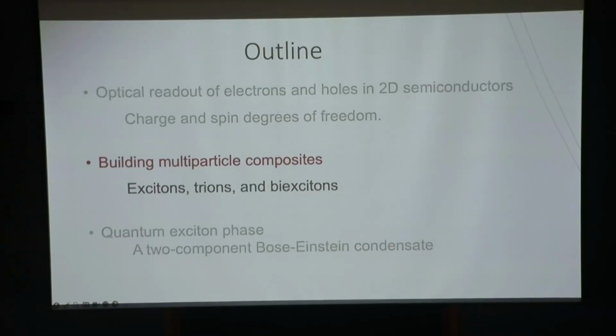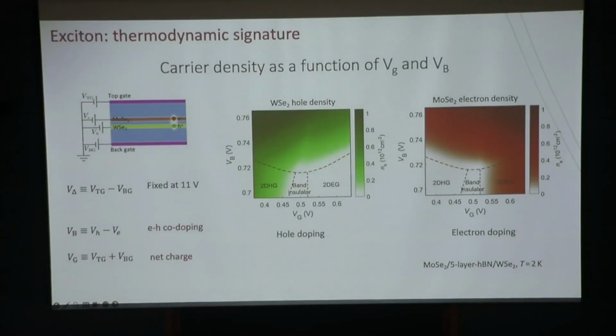Next, I will show you how we engineer these excitons, trions, and biexcitons, and in particular demonstrate that they really exist. It's not something in our imagination. So again, we start with this bilayer system, and we can inject electrons and holes here. The experimental condition is that we will fix the vertical electric field, which allows us to make the effective band gap of the two layers relatively small. And then we will use these two as our tuning knobs.